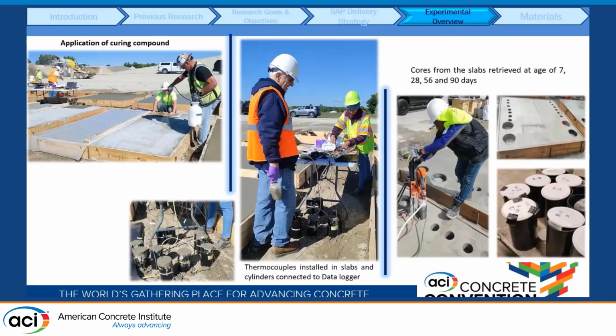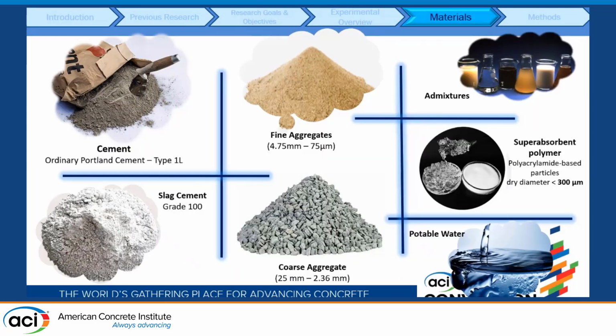And in order to evaluate the performance of the concrete mixtures under different curing regimes, 2 of the slabs, the reference slab and slab number 8 with 30% replacement of slag, were cured using a thin film curing agent, and the rest were air cured. Also, each of the slabs was instrumented midway with a thermocouple to measure the temperature variation and temperature history of the slabs. And cores were extracted from the slab at 7, 28, 56, and 90 days. The materials used were the traditional concrete making materials: cement, fine and coarse aggregate, as well as slag, admixtures, and then the addition of superabsorbent polymers.